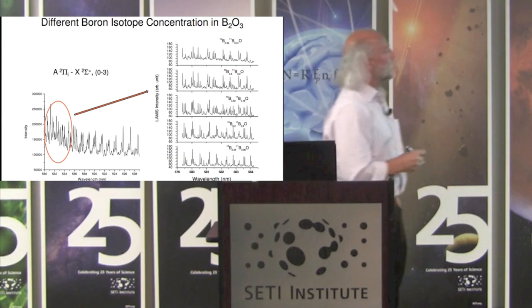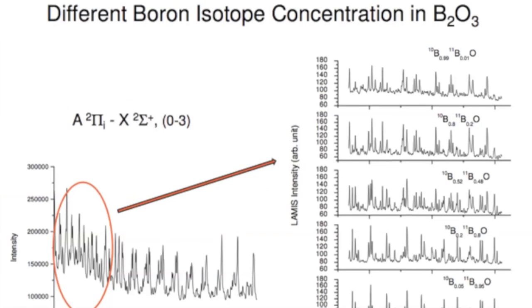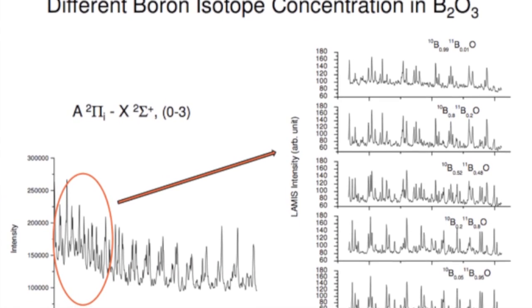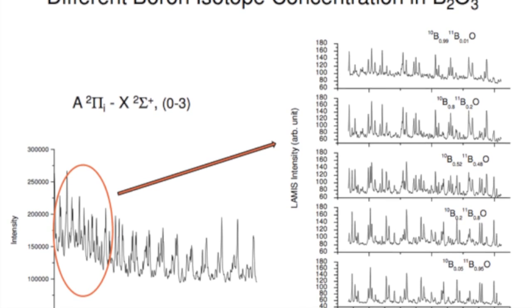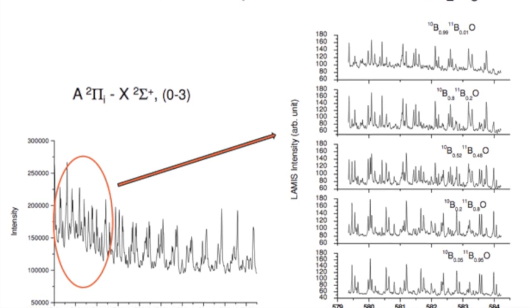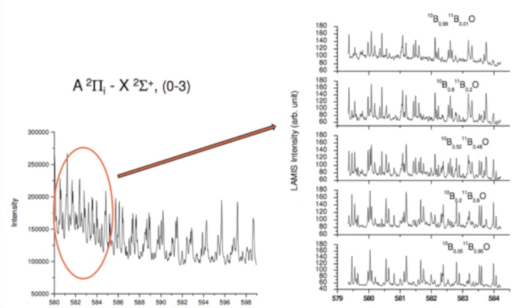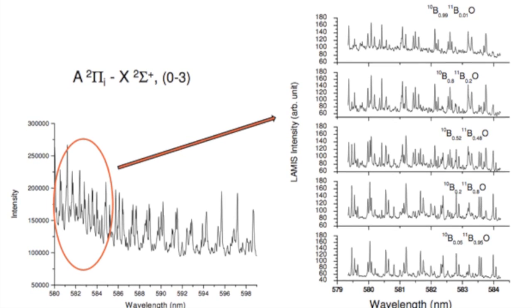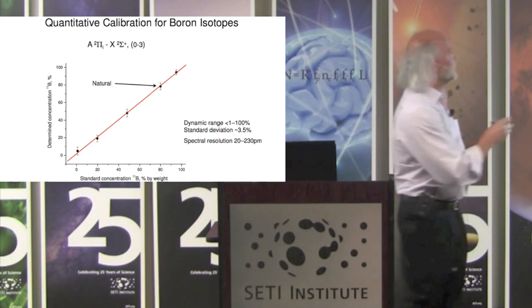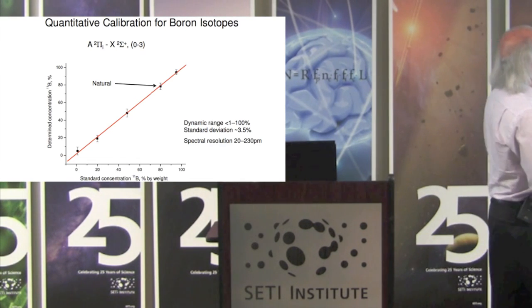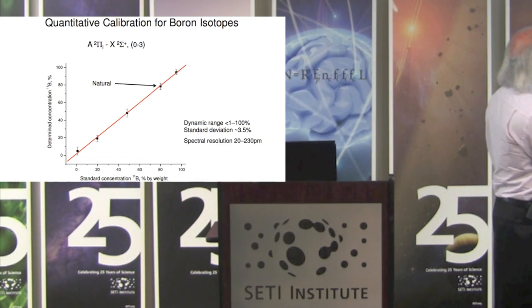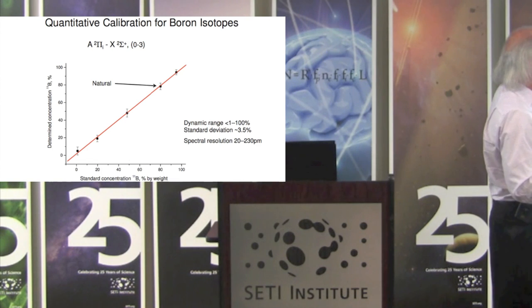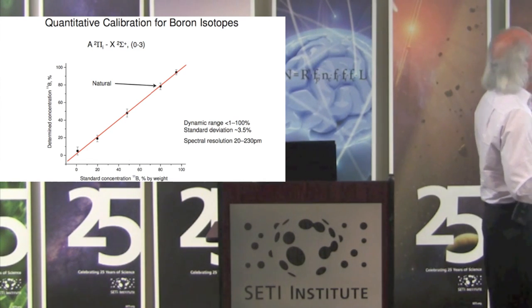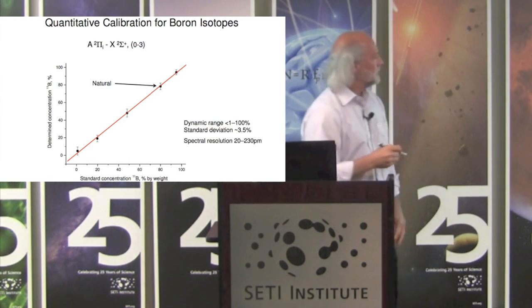Different boron isotope concentrations, we made anywhere from pure boron-10 up to pure boron-11. And again, this looks like hash, but you generate a database, you fit the spectra with a principal component analysis, and we're able to do the quantitative analysis of the isotope ratio. So that's a pretty darn good curve. Again, no sample preparation, hit it with a single laser beam, and we can tell you what the isotope concentration is.